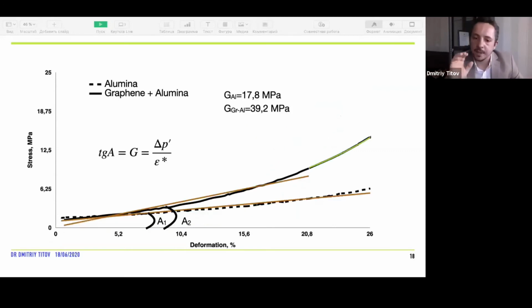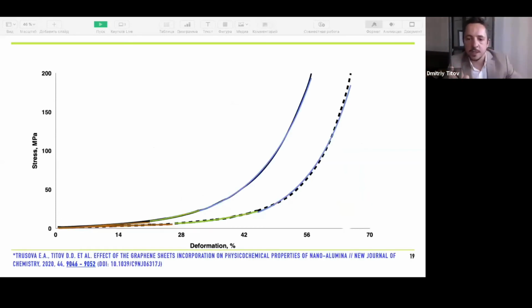Let's draw a trend line. The tangent of the inclination angle is equal to the modulus of compressibility. So the larger the angle is, the greater the elasticity of the powder. We see that the introduction of less than 2%, if talking exactly, 1.07 weight percent of graphene, leads to an increase in the elasticity of the powder of more than 2 times. Well, let's turn back to the whole curve here.